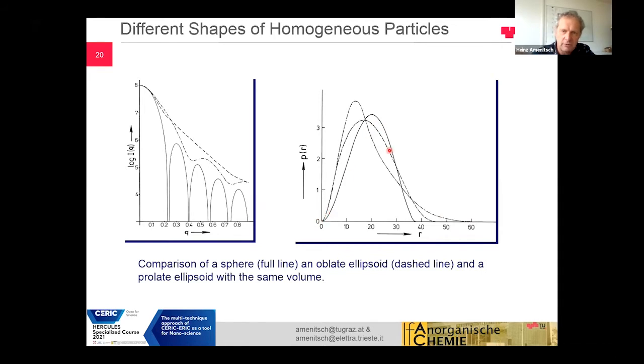And then it has somewhere a peak, and depending on the shape of the pair distance distribution function, you can immediately tell. So this is now an elongated particle, where you have here the cross-section term. And if you have this oblate ellipsoid, if you have this broadening of this bell-shaped curve for the spheres, you have somehow a broader peak, and then you have to do a certain transformation to learn about the cross-sectional or the thickness term of the pair distance distribution function.